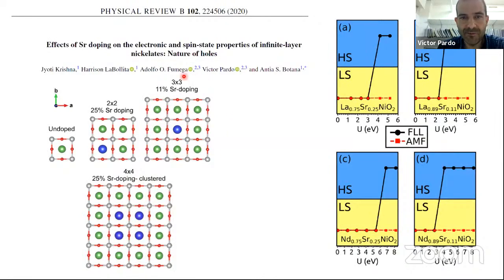So what we did for all of these was comparing the high spin and the low spin situation, and again with the AMF flavor of the LDA+U method, the way we introduce correlations, for all values of U, always the low spin is favored, for either lanthanum or neodymium, for the two types of doping. And again, for the other flavor that has this tendency to favor high spin states, yeah, at high U's you have it as favored. But again, our prediction from the calculations and from our experience with other nickelates, knowing that this flavor gives a better agreement with experiments, is that the dopants will be low spin.